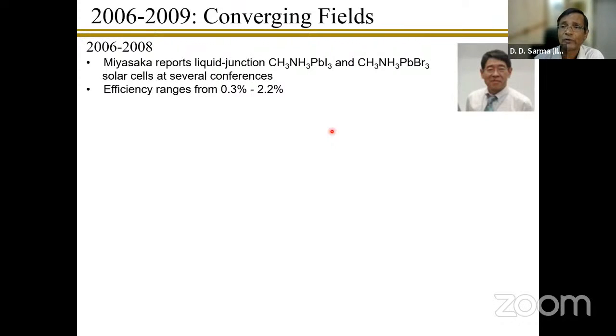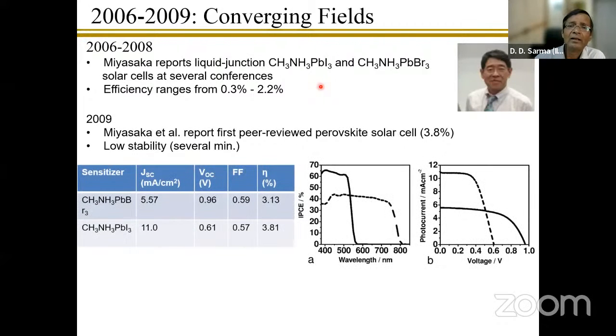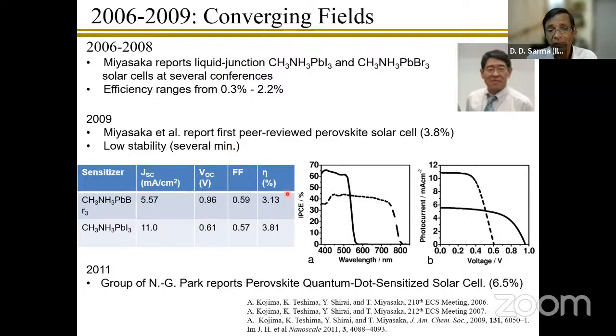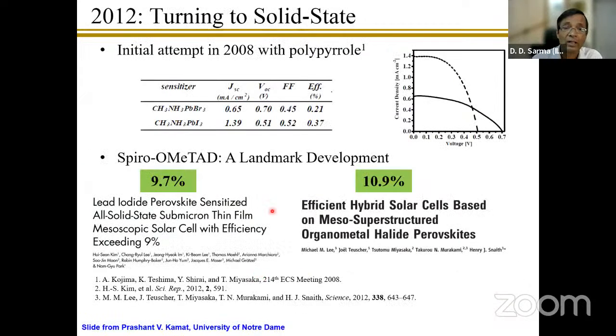This actually started, just to give you a sense of the history very quickly, around 2006, 2008. Professor Miyasaka in Japan was working with these materials. These are the materials that I'm going to talk about. And he could find very low efficiency, 0.3 to 2.2% or so. And it also had very low stability, only several minutes. Till Namgui Park's results showed a 6.5% efficiency. It still didn't catch the attention of the entire world till Namgui Park and Henry Snaith at about the same time showed that these materials can give 10% efficiency.